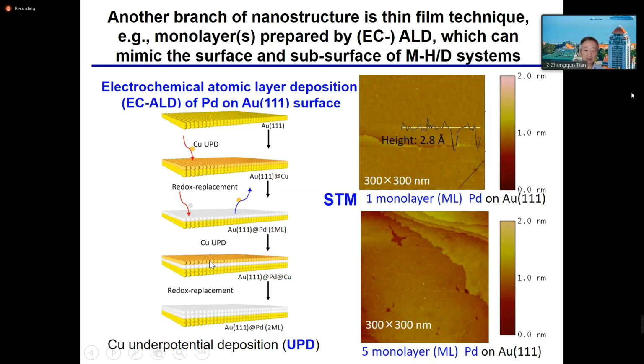Then we can go into the electrochemical way to have a second layer by UPD, then redox replace, layer by layer. So it's very, very well controlled, and we can get one more layer of palladium. The reason I want one more layer is that I just want to see what the hydrogen location is, because we all know that hydrogen can be absorbed by palladium. However, it cannot go into gold crystal. So the hydrogen has to stay somewhere. And that's the idea I really want to solve.